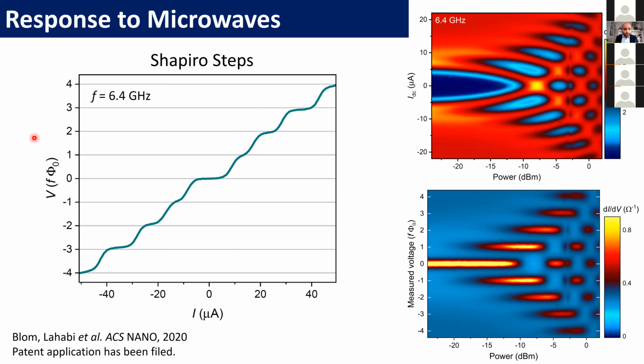And that would be, of course, this phi naught, the fluxoid. And that's basically what I'm showing you here. These are Shapiro steps taken from devices that were printed in the scanning electron microscope. And on the right panel, we also have the response of our junctions as a function of microwave power. So you increase the microwave power and you'll see all these Shapiro steps again. I think on the bottom panel, you see them more clearly, where they emerge as a function of microwaves.